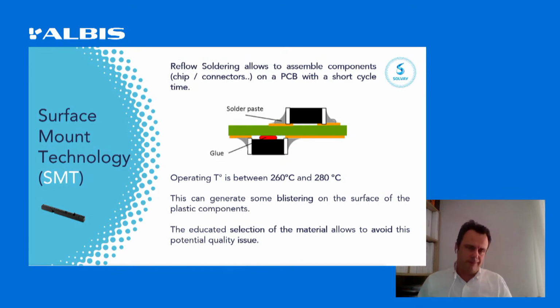And this high temperature can generate some blistering, some bubbles at the surface of the plastic component. This is not acceptable, and this is going to generate some quality issues. To avoid that, you need to have the proper material selection to be sure that your material is compatible with the different surface mount technologies existing today.